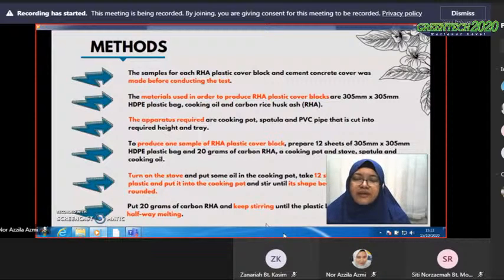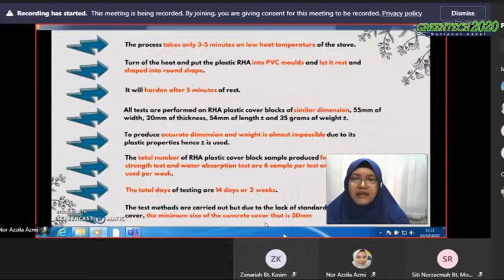Put in 20 grams of carbon RHA and keep stirring until the plastic RHA becomes halfway melted. The process takes only 3 to 5 minutes on low heat. Turn off the heat and put the plastic RHA into PVC molds and let it rest and shape into a round shape. It will harden after 5 minutes of rest.